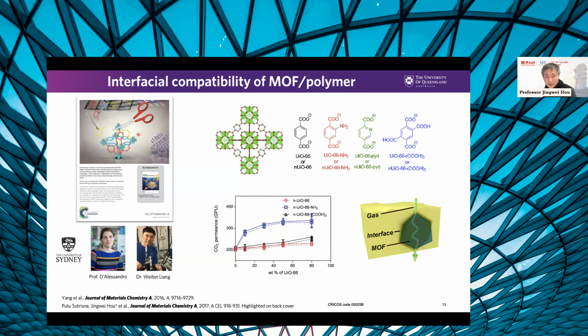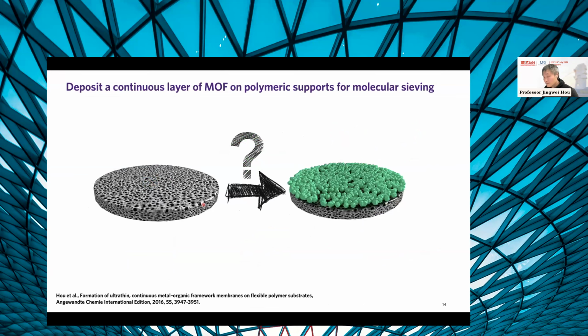So we published a paper and we highlight this concept. This is pretty much like designing the material based on our needs. So that's pretty exciting. So after working on the MMM, mixed matrix membrane, for a couple of years, I started to think, okay, if we believe the MOF material is such a good candidate for membrane, why wouldn't we just make a membrane out of the pure MOF, or at least use the pure MOF as a selective layer to make a membrane? So wouldn't that be a fantastic idea?